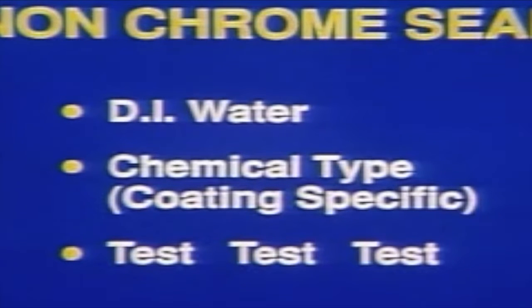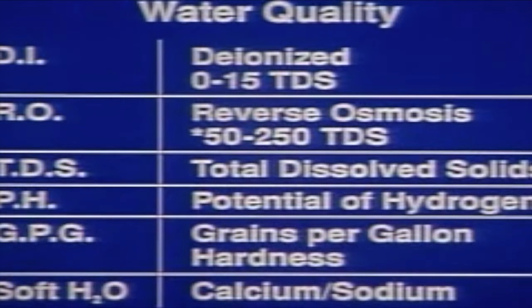You also need to review material safety data sheets to assure that other restricted materials have not been substituted for chrome. While none of the available non-chrome seal rinses can compare across the board to chrome for underfilm corrosion protection, deionized water has shown to be a good alternative in many cases. We would encourage the testing of deionized water whenever you are evaluating your pretreatment process. In the pretreatment and surface preparation, there are several steps that can be taken to improve the performance of your system while lessening the environmental control costs associated with waste disposal.